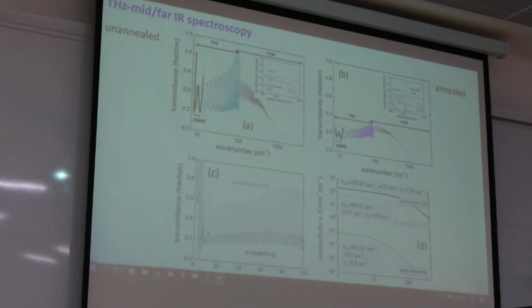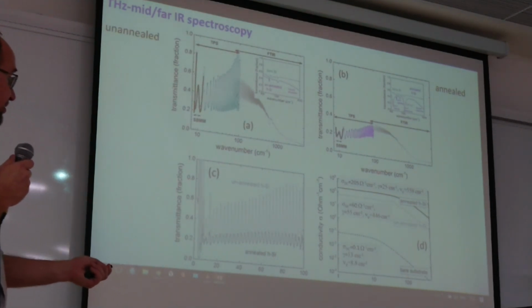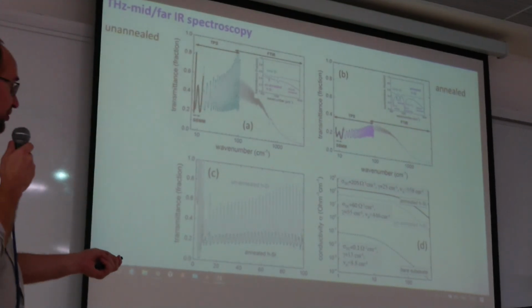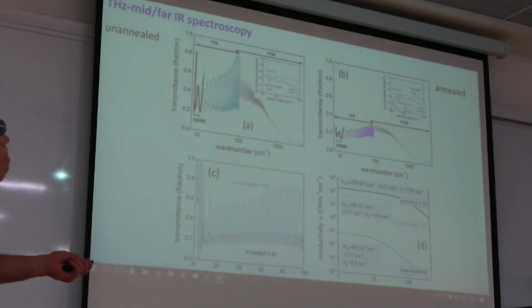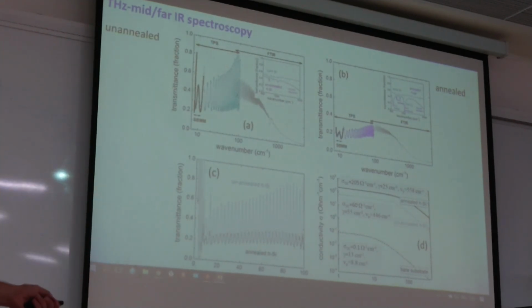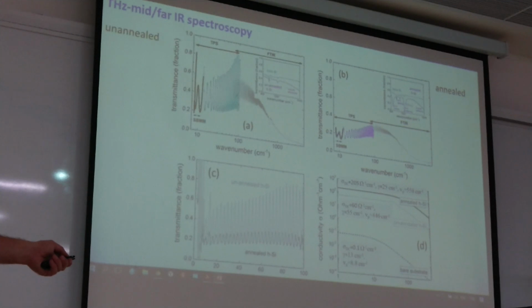from this spectrum characteristics like DC conductivity, scattering rate, and plasma frequency of annealed silicon, unannealed silicon, and even bare silicon. So we can see that plasma frequency is significantly higher for annealed silicon, but scattering is comparable. Scattering actually has an even lower gamma factor for the annealed one. Annealed material has a more regular crystalline lattice.